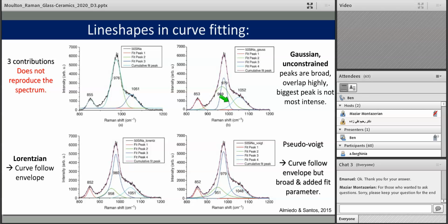Finally, on the bottom, you have Lorentzian line shapes and a pseudo-Voigt line shape. And just to show you the difference, here are the 4 peaks. Both of these fits reproduce the overall features in the spectra, but you'll see that when the pseudo-Voigt is used, you have quite broad line shapes, whereas when a Lorentzian is used, the peaks are quite narrow. There's still some overlap, which tells you that this overlap is real, not to be dismissed, but the centers don't overlap too strongly, which gives me confidence.